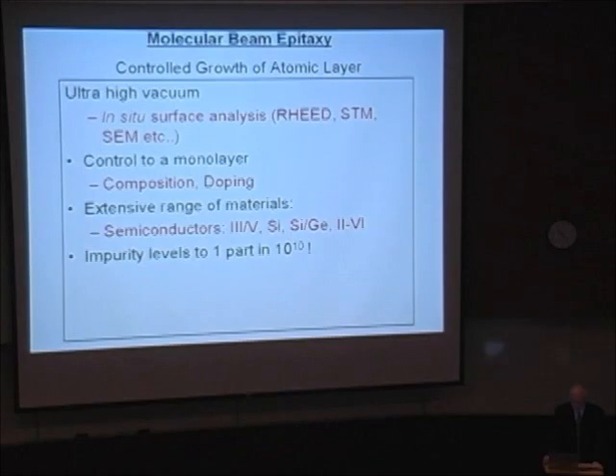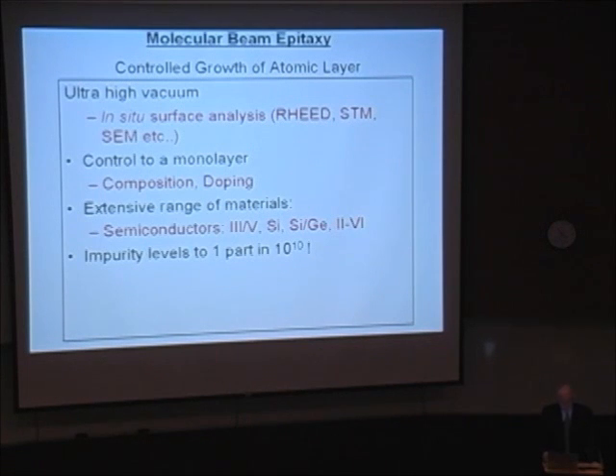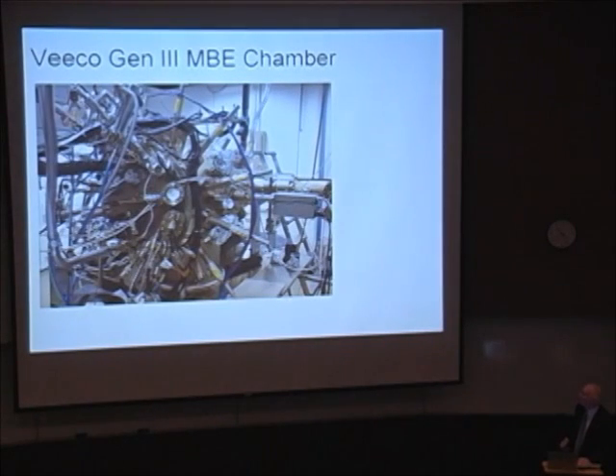So how do we make these nanostructures? Well, the common or garden method for making nanostructures in the most popular semiconductors, which are 3-5 semiconductors or 2-6s, is molecular beam epitaxy, which is a controlled growth, one atomic layer at a time. And this makes use of ultra-high vacuum. We have various techniques for surface analysis. It can be controlled to a monolayer and an extensive range of materials: 3-5s, silicon, germanium, 2-6s, metals. And impurity levels can be reduced to 1 part in 10 to the 10, which is really quite unprecedented for methods of crystal growth. This is, in fact, a Veeco Gen III MBE chamber.